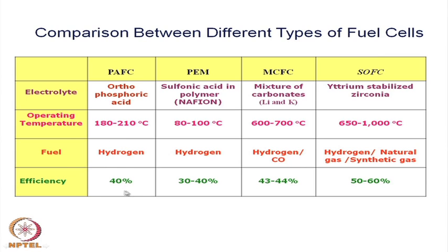Here the bulk part efficiencies have been put, about 40% here, 30 to 40% overall efficiency, and then 40 to 44% or 40 to 45, you can say, although it has been mentioned 43, 44 specifically, but it is around 40 to 45%, and solid oxide fuel cell can go as high as 50 to 60. Okay. This of course has some conditions, because one has to have utility of the thermal energy also. We will look into that, what exactly it means.